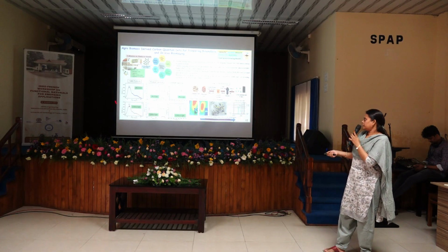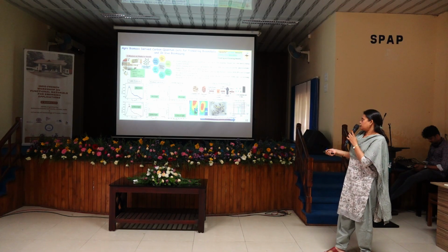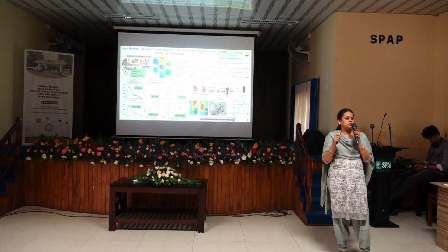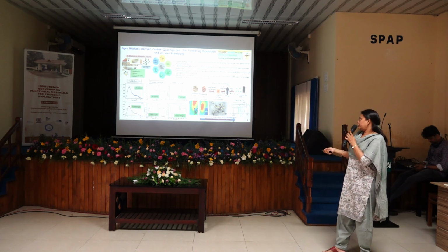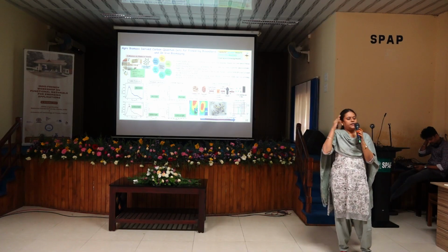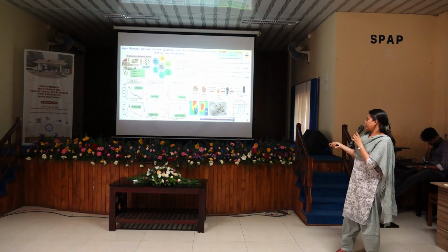So the XRD pattern for both pistachio and groundnut shell CQDs shows an amorphous nature, and both have Raman spectra with more intensity in the D band, because the defect band is more due to the silica content in the groundnut and pistachio. The FTIR spectrum also shows the carbonyl and hydroxyl groups interacted with nitrogen, oxygen and hydrogen.